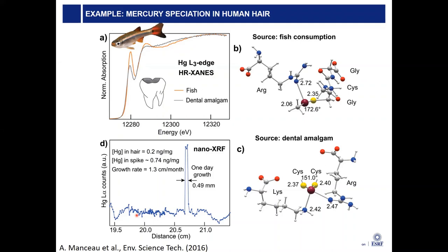Below here, you see actually measured at ESRF ID21, with an X-ray microscope, if you scan along the hair in this direction, and suddenly you see the spike here, that means you can calculate back when the dentist removed the amalgam, because this is when you've got the mercury in your body, and then the hair grows, and then at a certain point in your hair, you find it again. It is very low concentration. This is in the low parts per million, ppm range, to measure those data.